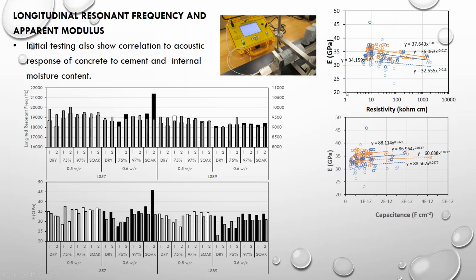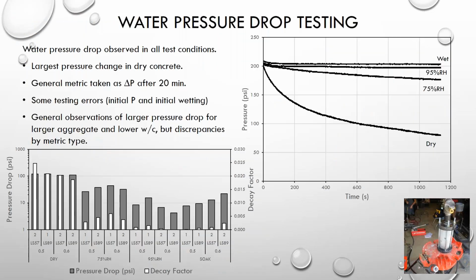And similarly, again, when we plot them in terms of the modulus to resistivity, modulus to capacitance, we again see some differentiation between the water cement ratio and the rock type. Again, the 0.6 being blue, 0.5 water cement ratio being orange, and the dashed line being the LS89 rock, and the solid lines being the LS87 rock. So we're seeing some separation. Again, ideally, we can correlate this to water pressure drop with the testing that we have at hand.